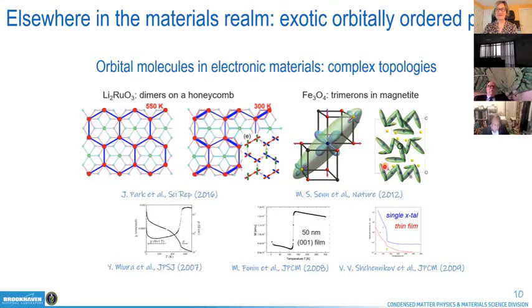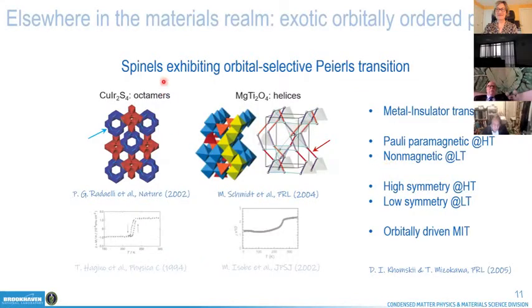So that being said, with all that complexity, I'm going to focus on two related spinels that exhibit orbital selective Peierls transition. This is copper iridium 2 sulfur 4, which exhibits octamers, and the titanium version, magnesium titanium 2 oxygen 4, that displays helices. I'm not going to be concerned with the specific topology of the low temperature phase as such. Both systems exhibit metal insulator transitions. They are Pauli paramagnetic at high temperature and non-magnetic at low temperature, and the symmetry changes from high to low across the transition. This behavior is assigned to an orbitally driven MIT.